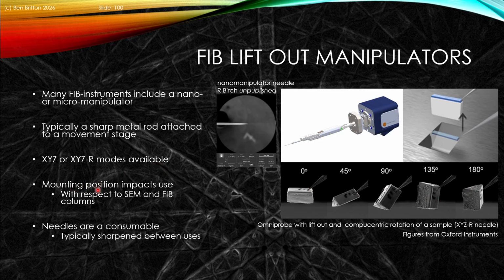The specific mounting position of this manipulator underneath the instrument and where it is with regards to the SEM and FIB columns will impact the use. And we just recognize that these needles are consumable. It depends on the particular setup, but they can be maybe $100 or more per needle depending on which ones you're using. And we'll also typically, depending on what we're doing, we might sharpen or control the end effector of that needle in practice.